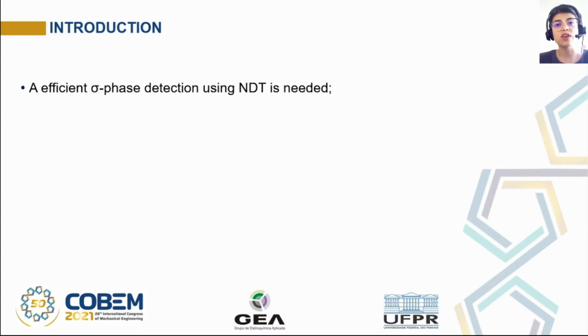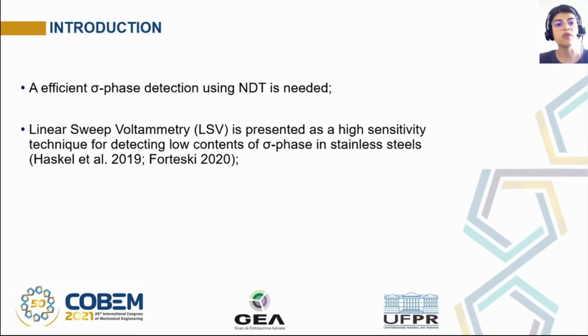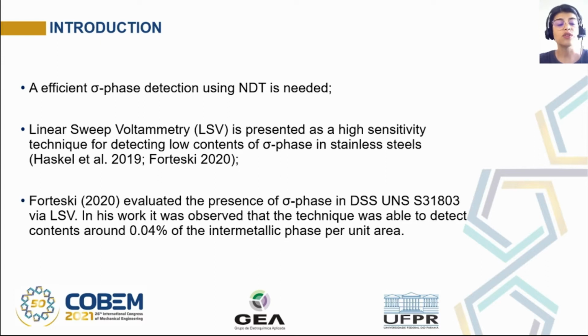We have a lot of methods for sigma phase detection, but most of them are destructive testing, and we need efficient sigma phase detection using a non-destructive test. Linear sweep voltammetry is presented as a high sensitivity technique for detection of low contents of sigma phase in stainless steel. Forteski 2020 evaluated the presence of sigma phase in DSS UNS S31803 using linear sweep voltammetry. In his work, it was observed that the technique was able to detect contents around 0.04% of intermetallic phase per unit area.